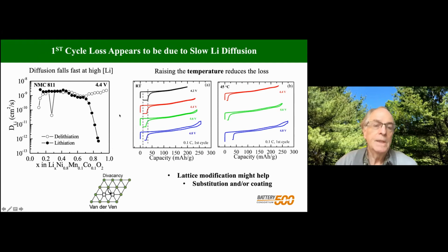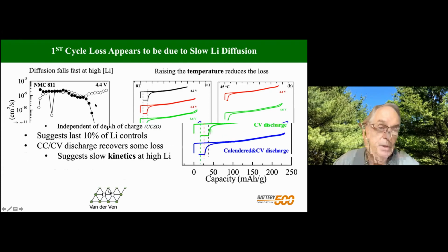So we measure the diffusion coefficient. The black is the indiffusion, and you can see above about 80% lithium, we're seeing a 2 to 3 orders of magnitude drop in the lithium diffusion coefficient. And Anton van der Ven relates that to the diffusion mechanism, which he says is a divacancy mechanism. So what you need is 2 vacancies for one lithium to jump through a tetrahedral site to the neighboring octahedral site, and the number of these drops off dramatically as the lithium content increases.